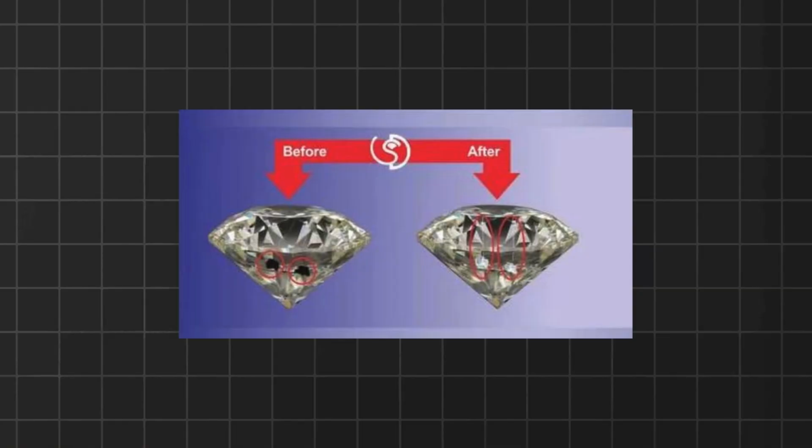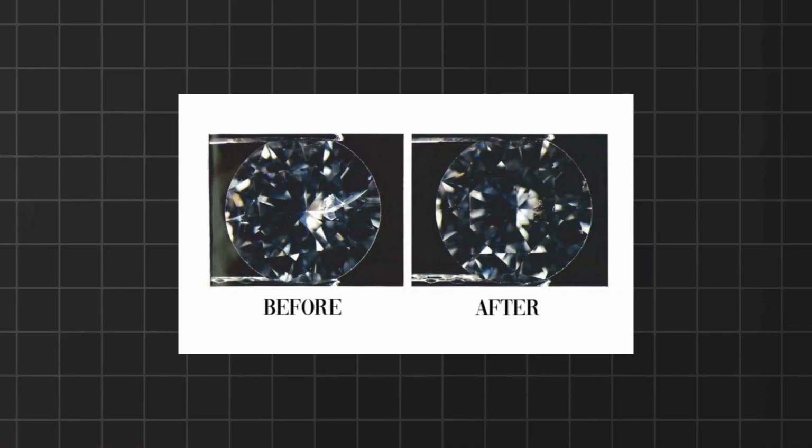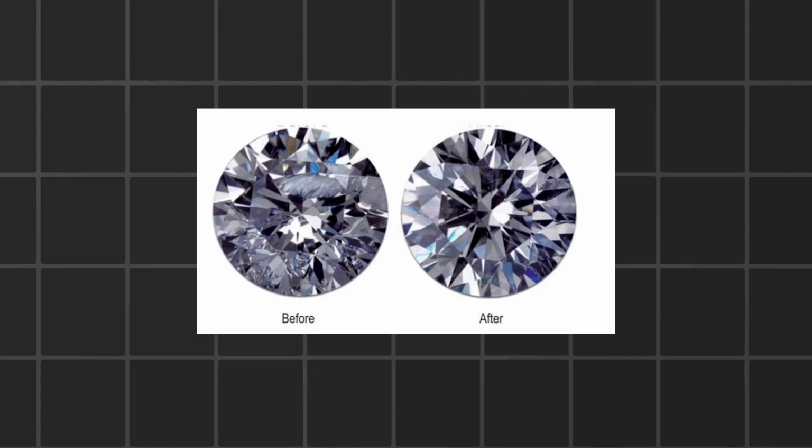It is very, very important to have a high refractive index glassy material which looks very similar to a diamond, because if it's going to look very different and has a low RI, which is refractive index, then it's going to look completely different, like an inclusion, and we do not want that. We want the stone to look really pretty and enhance the features and look glossy and flawless, and that is exactly why we are doing the entire treatment process. So it's important to have a glassy material which has a high refractive index during this procedure of crack filling a stone.